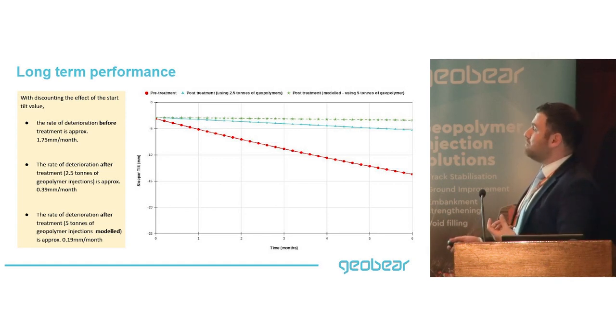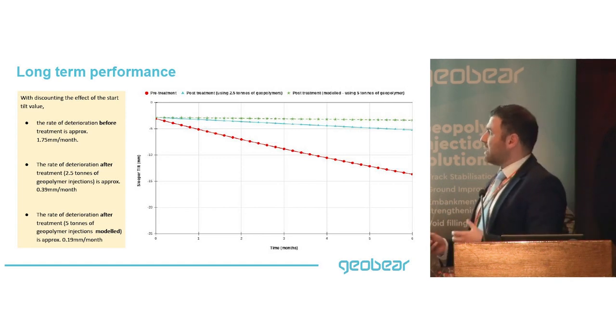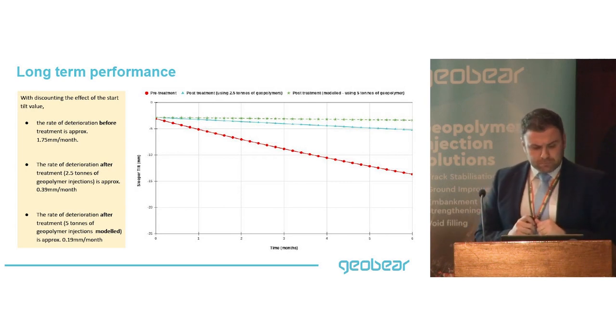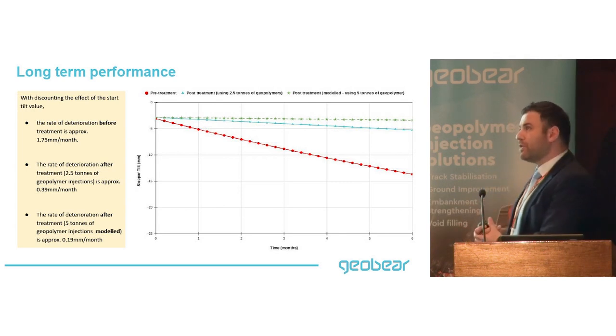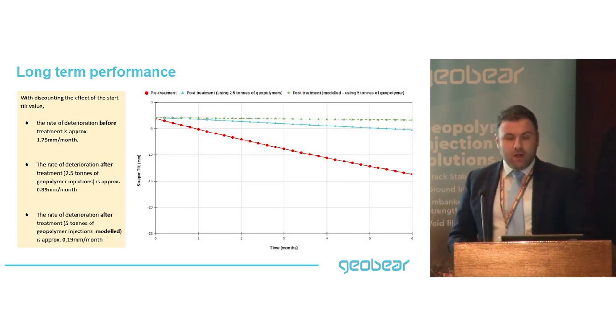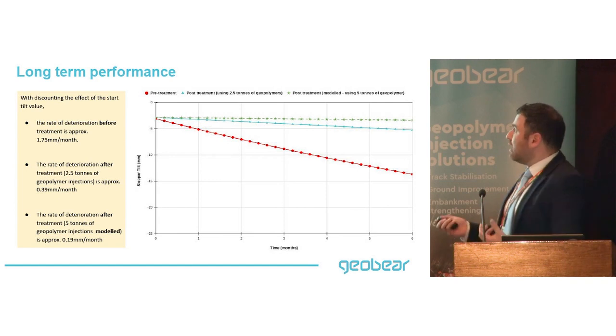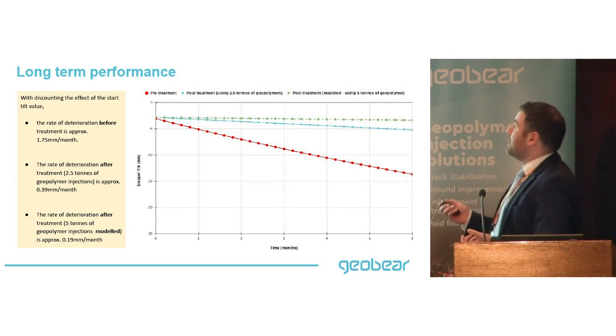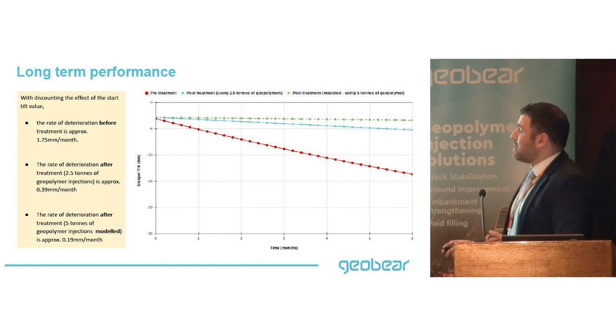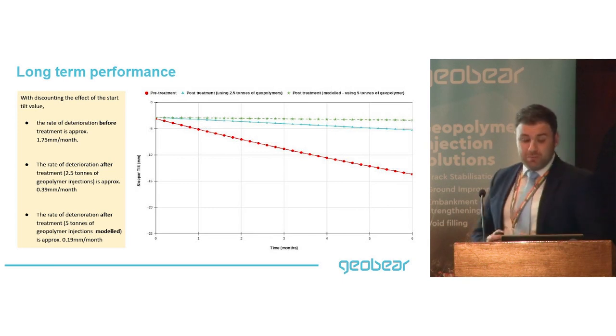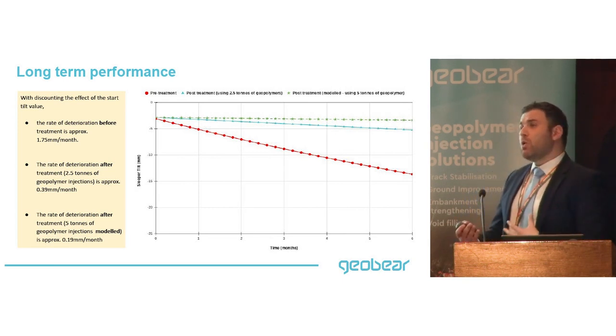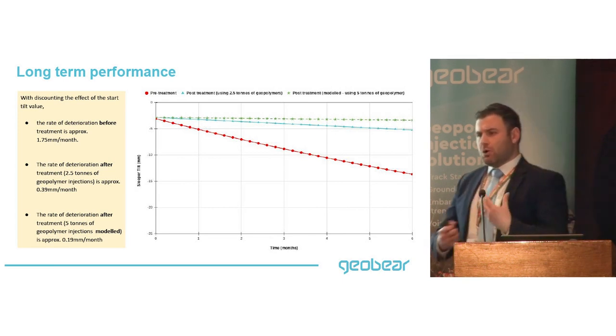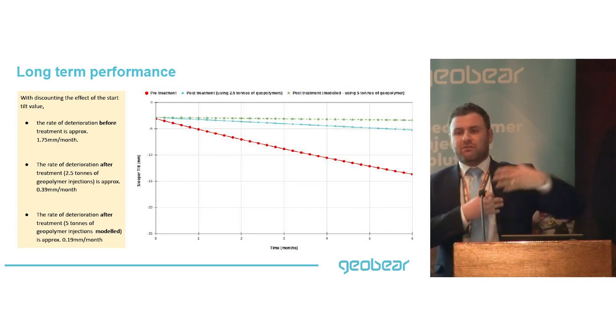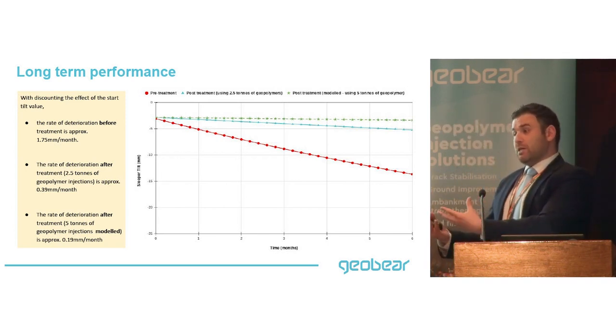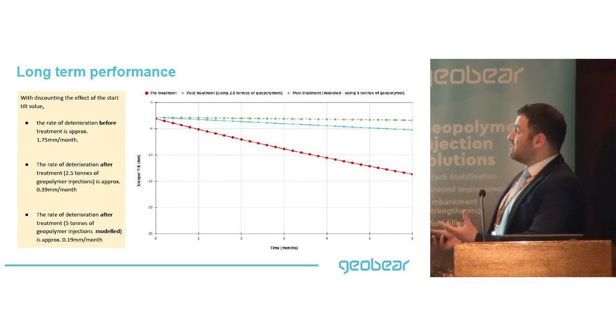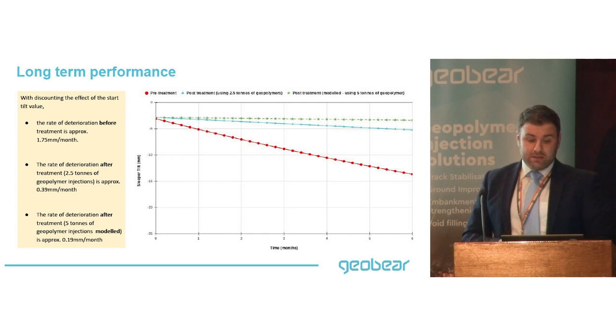And this was using 2.5 tons of material, which gave us this level of degradation. If we were to go with a full-blown design, we would have gone for 5 tons of material, and we actually modeled what would have happened - we would have managed to reduce that to around 0.2 millimeters a month. So it really depends on what the client requirement is and what sort of degradation levels you're after. We can probably come up with a design that provides that target.